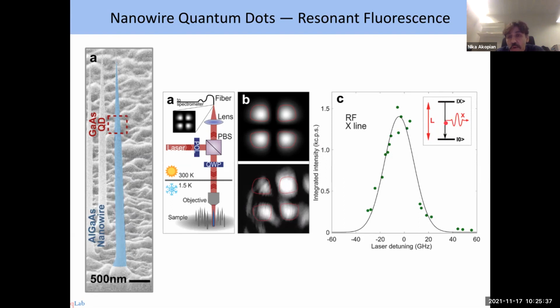So people use cross-polarization excitation. The excitation of the laser has one polarization, and the emitted photon has a different polarization. By distinguishing the polarization, if you do it carefully enough, you can distinguish this single photon from the reflected laser. So what's the problem with nanowires? With as-grown samples, the problem is actually not the nanowire, but the surface. You see, the surface is always rough, and it means it will change the polarization of the laser. So if you come with a certain polarization and you want to distinguish after reflection, it will actually not be as good. That's the challenge here. But we have shown that it's actually possible. By carefully doing this, even though the surface degrades your rejection quality, it's still possible.